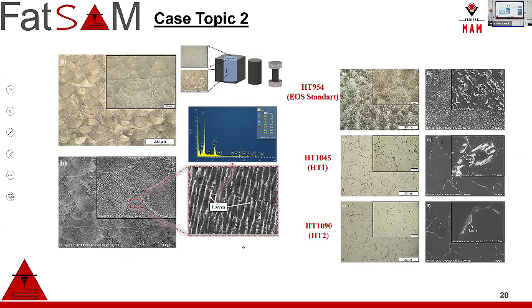Anyway, we look at the compositions. As I said, we couldn't escape from the Laves phases. Even after creep and heat treatment, with Laves phases, we saw some delta phases as well. But after heat treatments, we have a much more ordered morphology after homogenization and heat treatment. Newly nucleated grains appear after recrystallization because of the annealing. We have annealing twins as well. With higher temperature heat treatment, we have much more equiaxed grain formation.